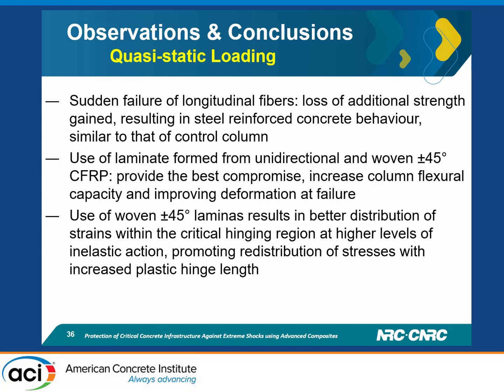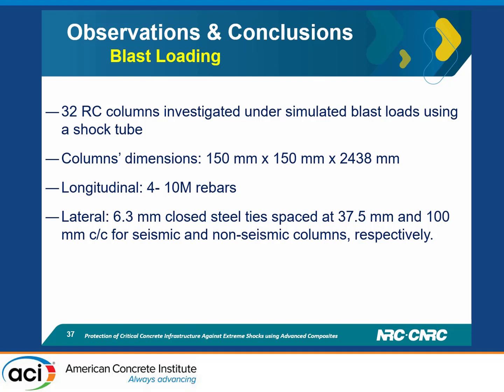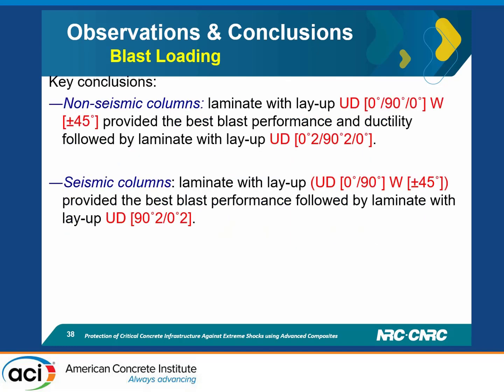Now, using woven plus minus 45 improves, of course, the ductility, and we developed a new calculation for the plastic hinge when it is used with a single degree of freedom simplified analysis model. Parallel to that, this summarizes the blast test. In the blast test, we compare again the different layups, and we found that the layup I mentioned, 0.90 plus minus 45, gives the best behavior in terms of the highest energy absorption, better ductile behavior, etc.